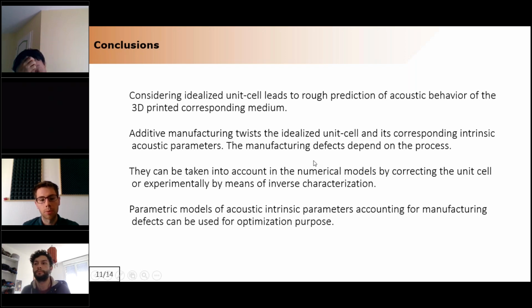But these defects are only a problem if you cannot take them into account in your simulation at the end. What we have seen is that we can consider them numerically by changing the unit cell considered in the numerical simulation, or experimentally using some inverse characterization of a homogeneous sample. At the end, you get a parametric model of the intrinsic parameters of the homogeneous material that is reliable and corresponds to the experimental data. And of course, you can use it for optimization purposes, of gradient of properties for instance, or many other applications you are free to use.